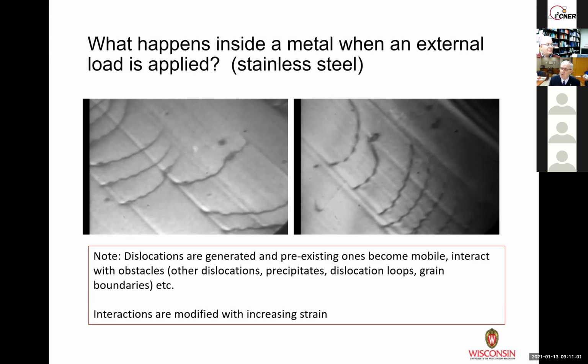What's responsible for the change in the interaction is that one dislocation interacts with the precipitate, it passes the precipitate, but it leaves something behind. So though we cannot see it, the precipitate form does change as more and more dislocations go past it. And you actually require a different mechanism for the dislocations to bypass with increasing strain.